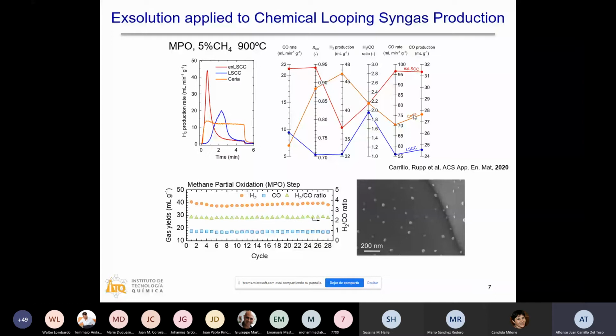And we also carried out the stability test and saw that after 28 cycles, hydrogen and CO production is quite stable and the particles are still there, which is quite good news. And when I was looking at the top left image, I was wondering if we can also do that to ceria. Can we actually apply the exsolution method to ceria to improve the kinetics of the process? And this is what motivated me to start with this new research that I'm carrying out currently. So let's move to that.